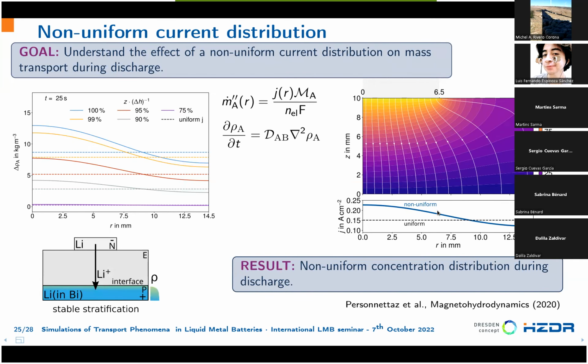And this non-uniform current distribution in discharge results in a non-uniform concentration distribution. So we have more lithium concentrated here in the core of the cell and less on the side. So the dashed line here is with uniform current distribution, and the continuous line is with non-uniform current distribution.